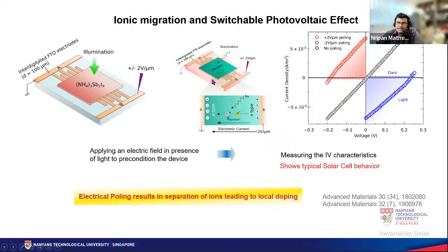The current just passes through at 0 volt. But once you apply a poling voltage, you can see that you are able to switch it such that there is an inbuilt voltage within this system. This inbuilt voltage comes because when you apply voltage for a long time, the halogens can start to diffuse within it and dope one end p-type and another end n-type. So you could have a self-doping mechanism active within these perovskite systems, which again gives us another knob to turn to try and utilize it.